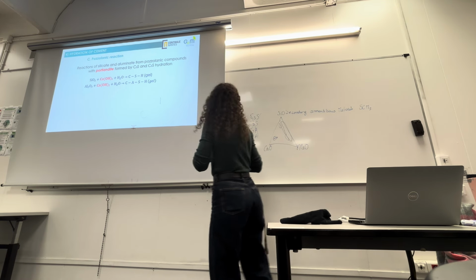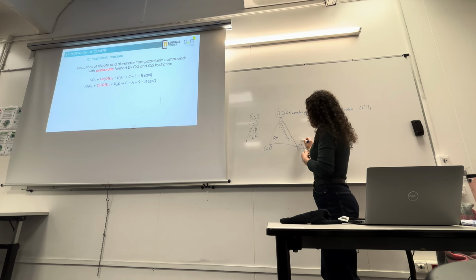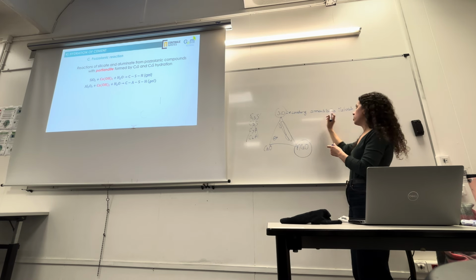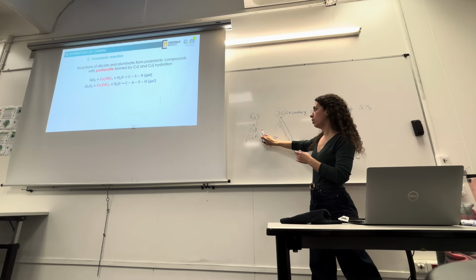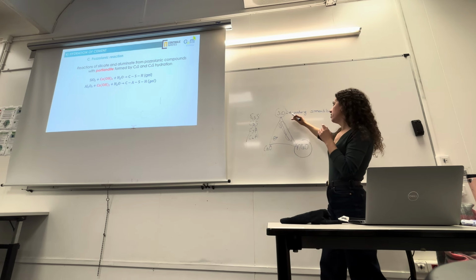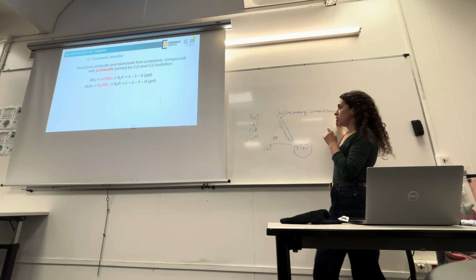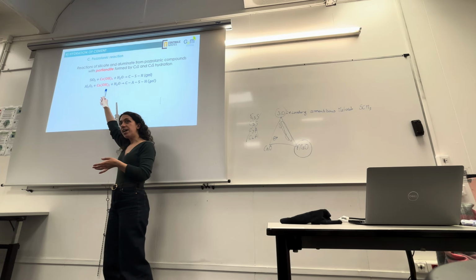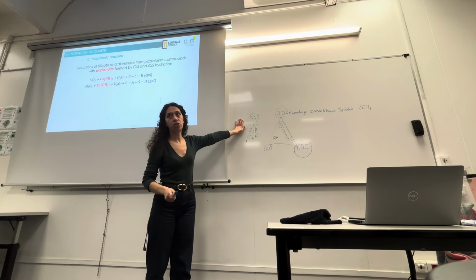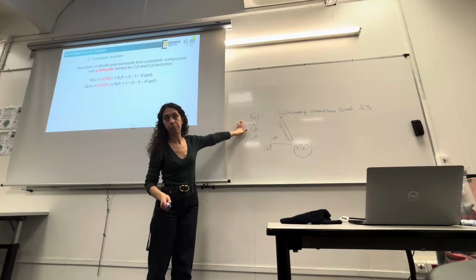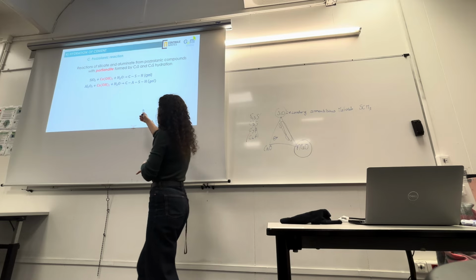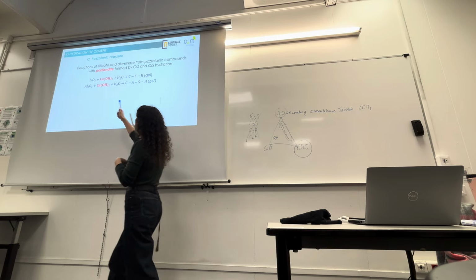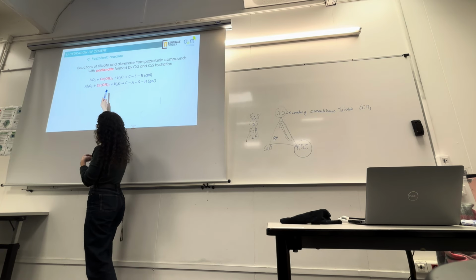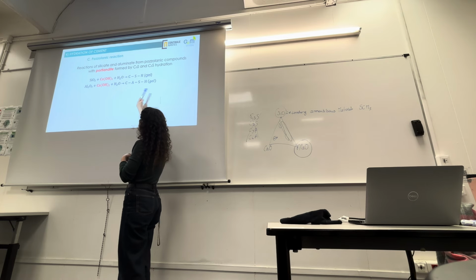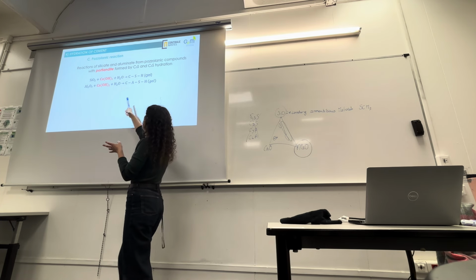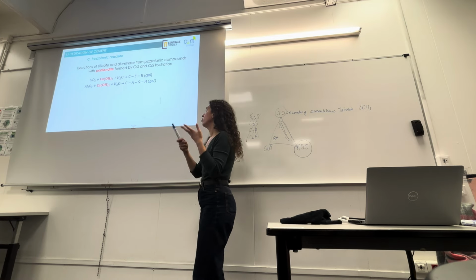Because what is the pozzolanic reaction? It is the silicate and aluminate from the secondary cementitious material, not from the clinker. The silicate and aluminate from the secondary cementitious material will react with portlandite formed during the hydration of clinker. Okay? And then we form, once again, CSH by the reaction of silicate with water. And if you have aluminate, you will also form CASH. So CSH and water.